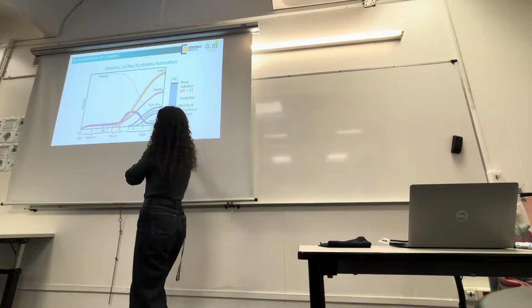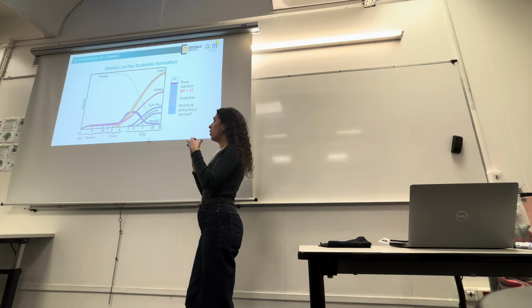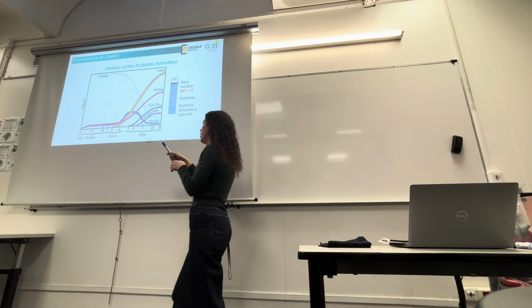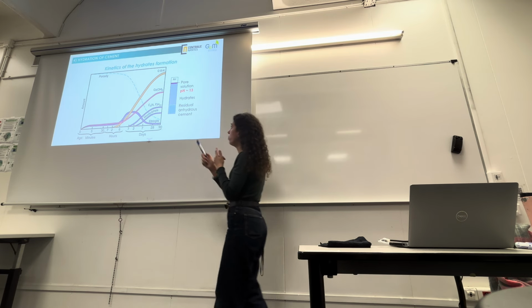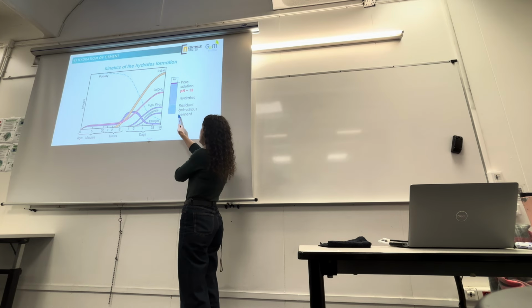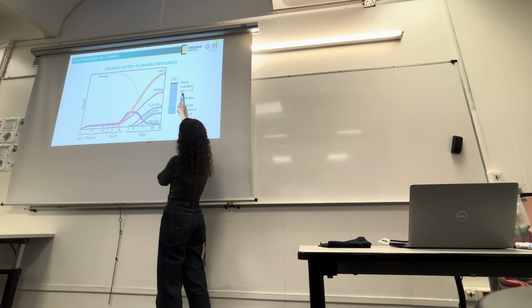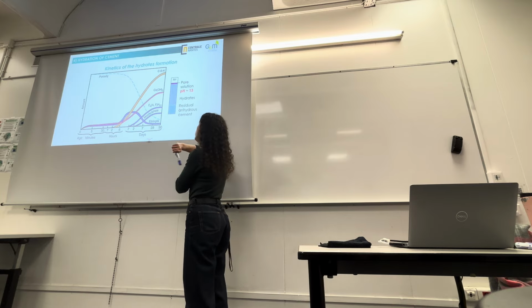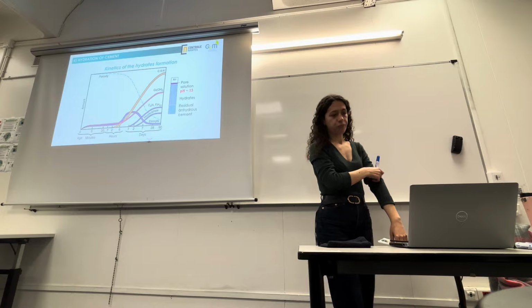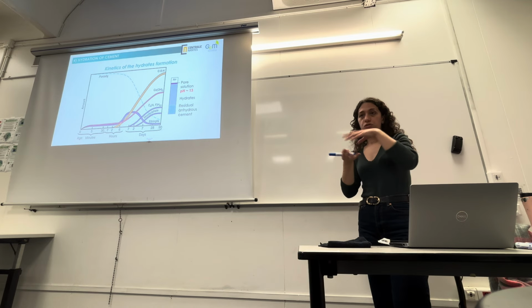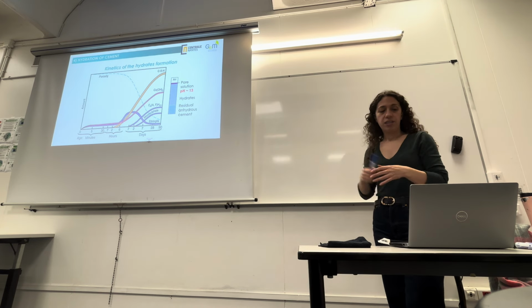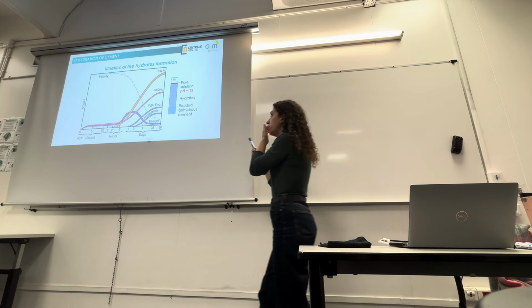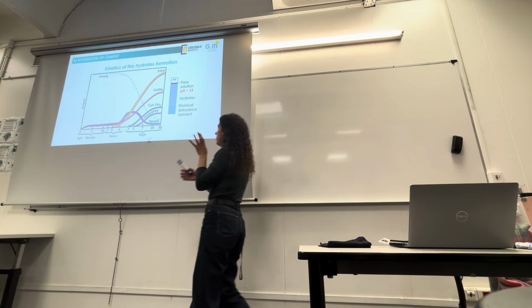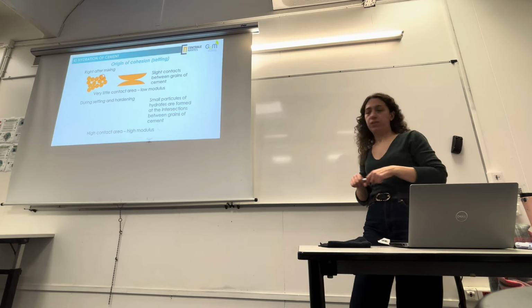So this is the composition, and at the same time you see a decrease of the porosity of your cement that is filled with the precipitation of hydrates. So this is the composition of your cement paste, you have residual anhydrous cement, mostly hydrates. You have the porous solution with a pH of 13. Remember that it's important. And you have air voids inside your material. Because even though we try to vibrate, to tap the material, there is still air that is present inside the material. So these are the different parts of the cement paste: air, porous solution, hydrates, and residual anhydrous cement behind the hydrate layers.